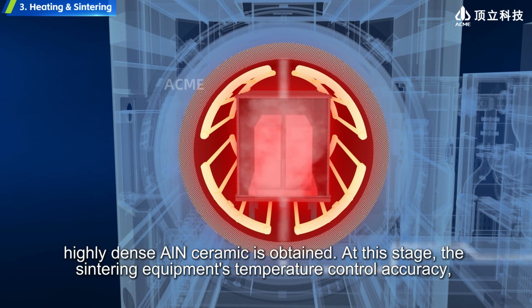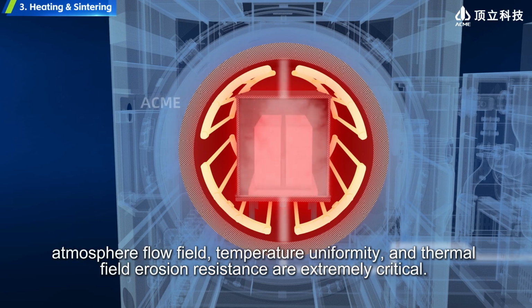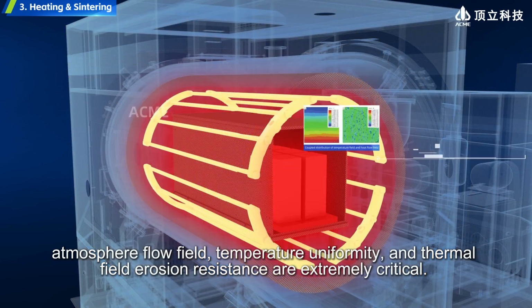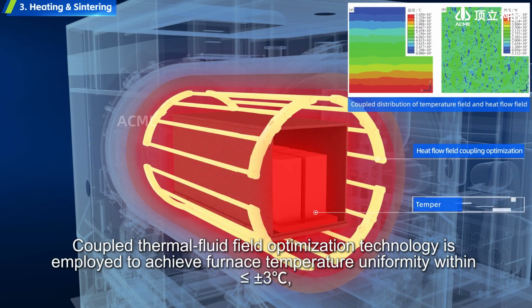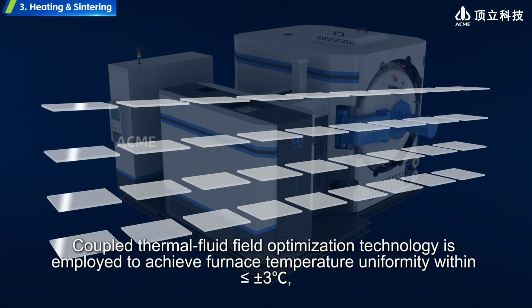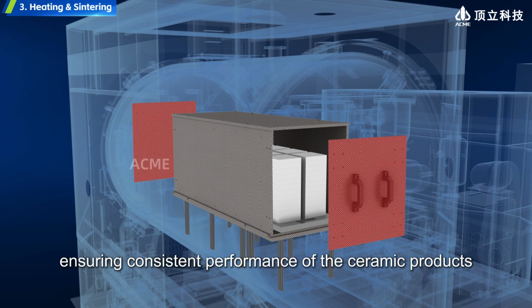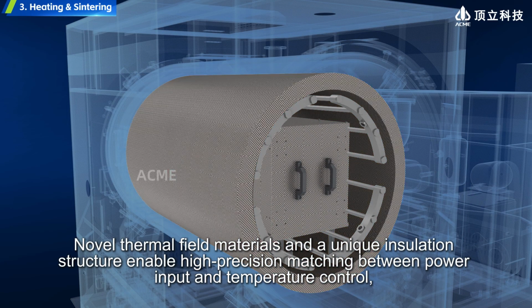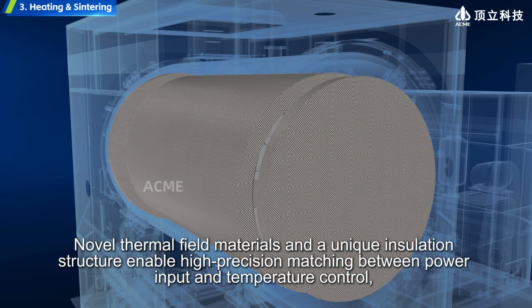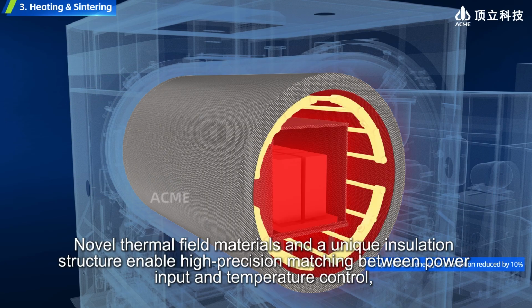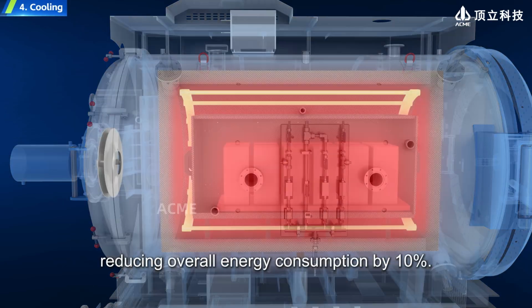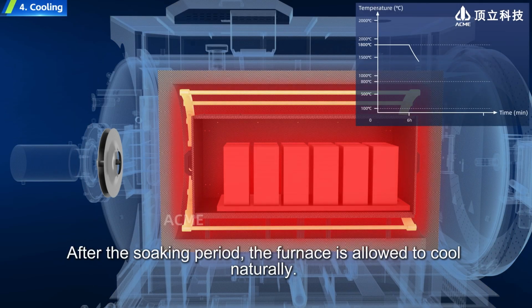At this stage, the sintering equipment's temperature control accuracy, atmosphere flow field, temperature uniformity, and thermal field erosion resistance are extremely critical. Coupled thermal fluid field optimization technology is employed to achieve furnace temperature uniformity within less than or equal to plus or minus 3 degrees Celsius, ensuring consistent performance of the ceramic products. Novel thermal field materials and a unique insulation structure enable high-precision matching between power input and temperature control, reducing overall energy consumption by 10%. After the soaking period, the furnace is allowed to cool naturally.